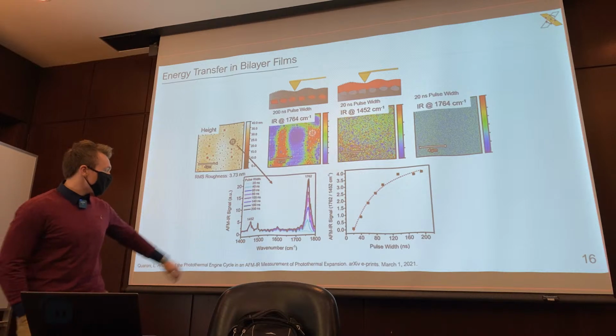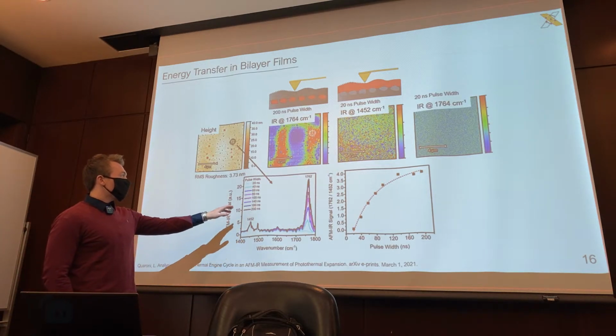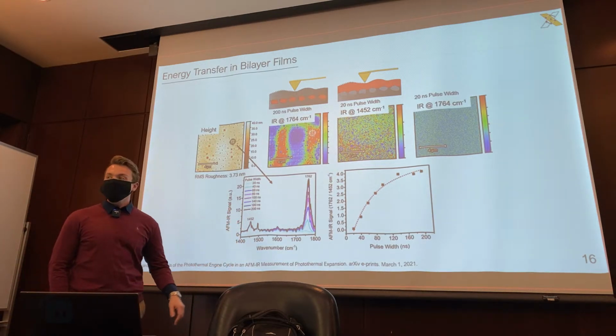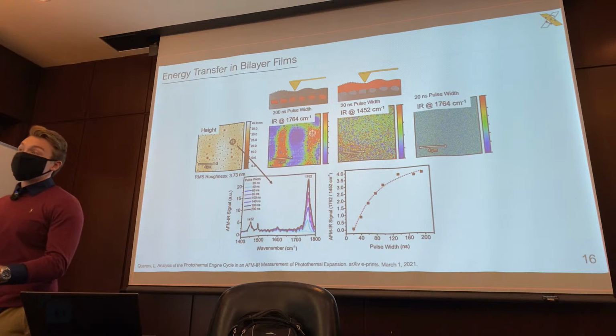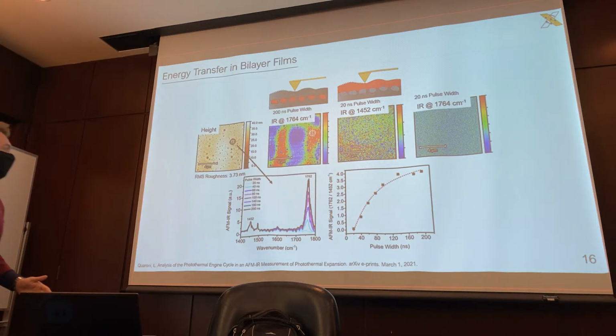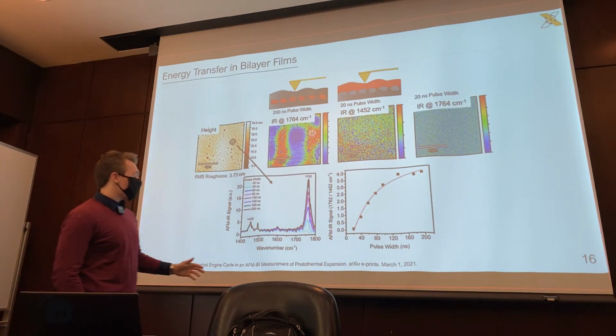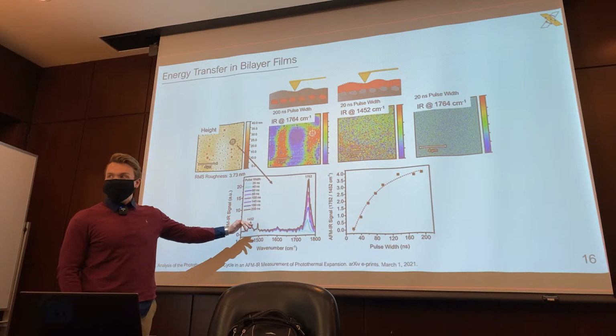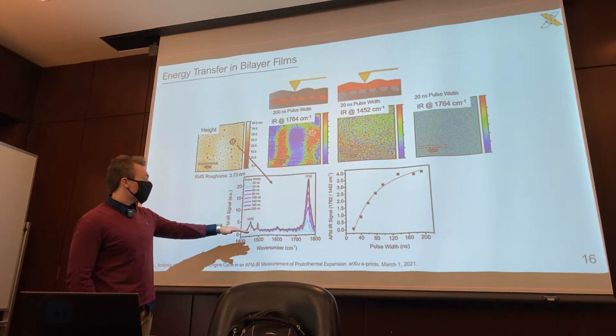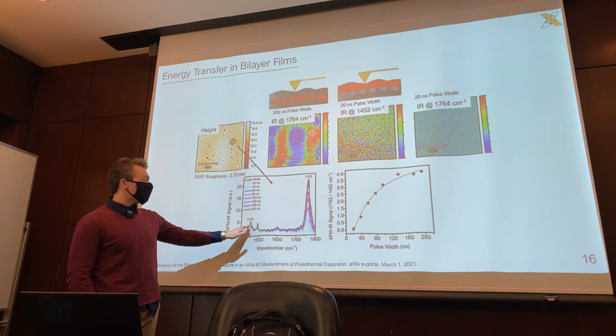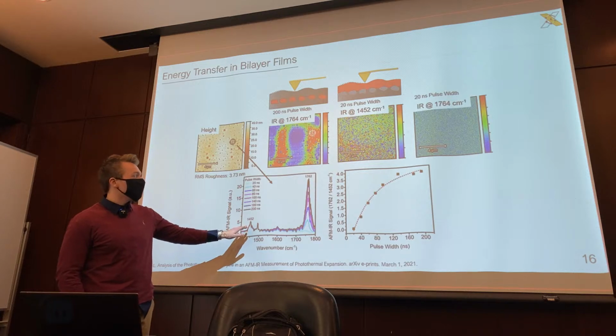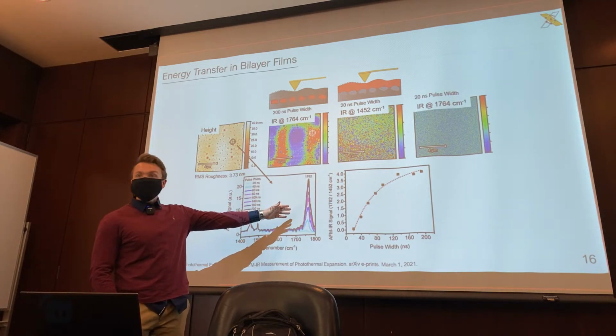Right. What I did here is, because when you reduce pulse width, you're also reducing the amount of energy that you're putting into the system, if you didn't normalize it, you would see this decay automatically from all. So I needed to normalize this at 1452 to see the effect on just 1764.